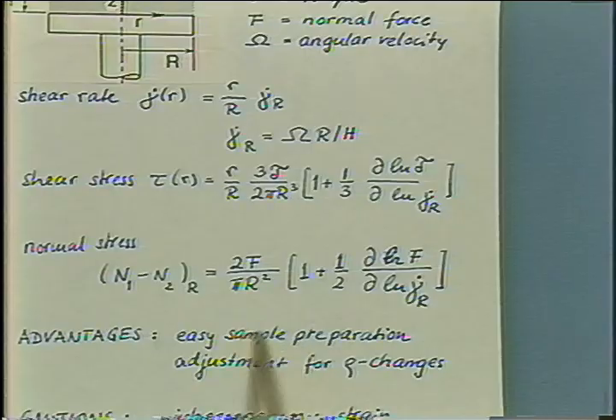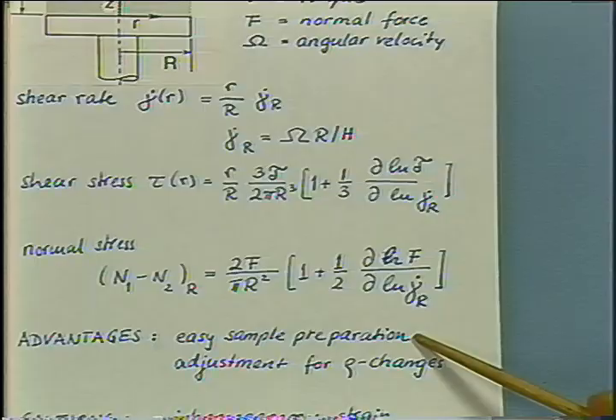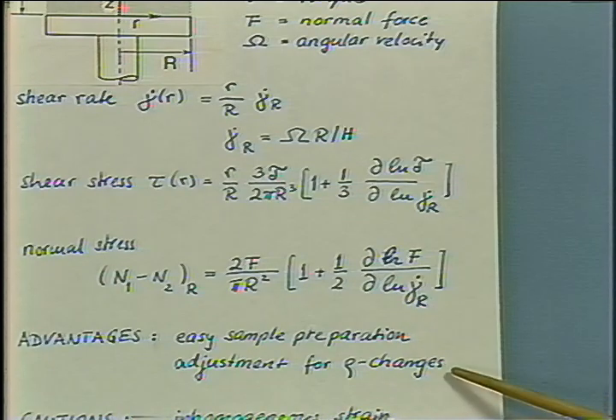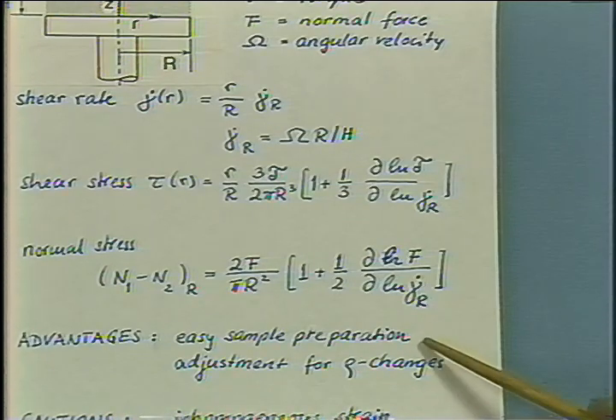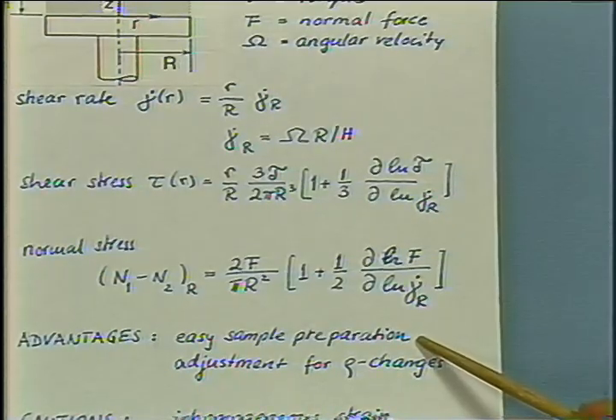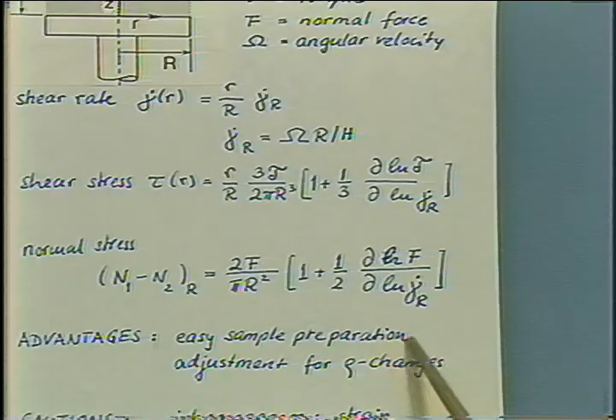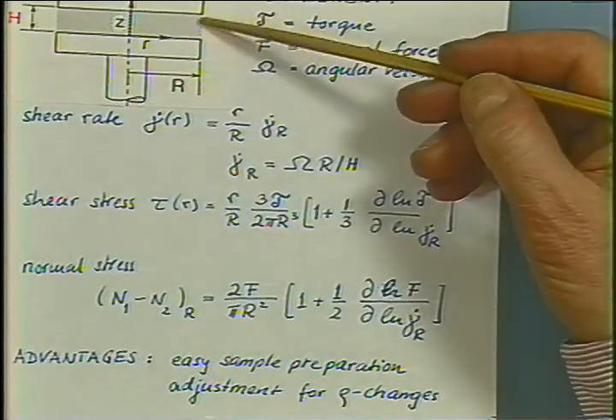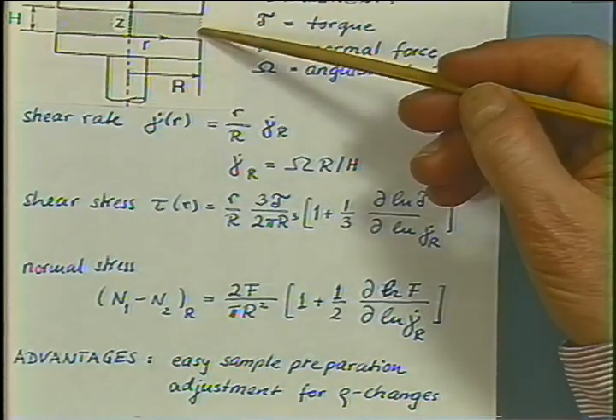So the advantages are the easy sample preparation, which is in some cases essential. Imagine you work with suspensions. You cannot push a cone into a suspension and maybe grind some particles between them. Or you have a sample which has some interesting microstructure. You would not want to disturb this microstructure by pushing a cone into that system. So you can prepare your sample very carefully, and you can adjust your gap setting as your sample maybe shrinks or expands with temperature changes.